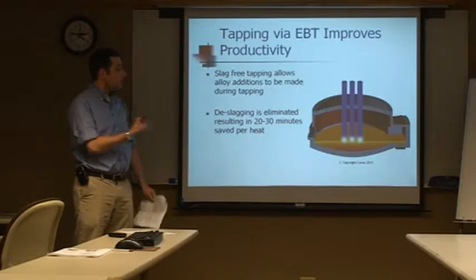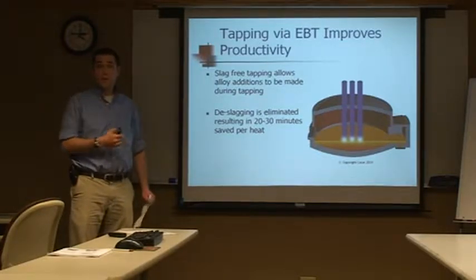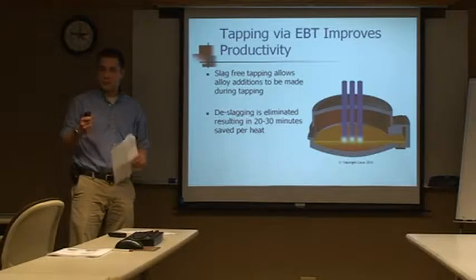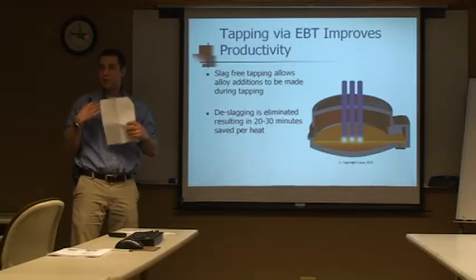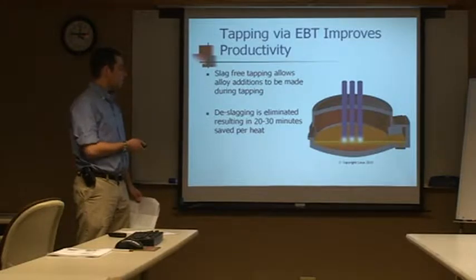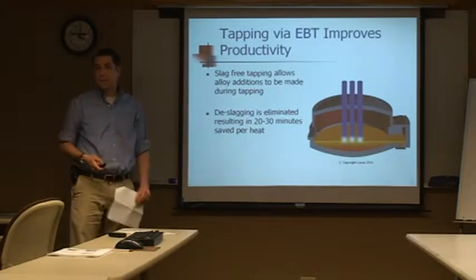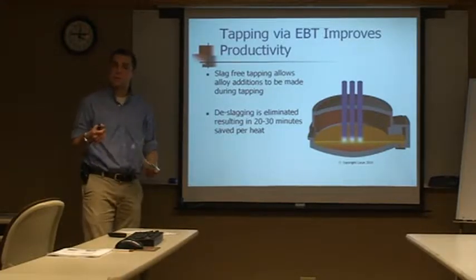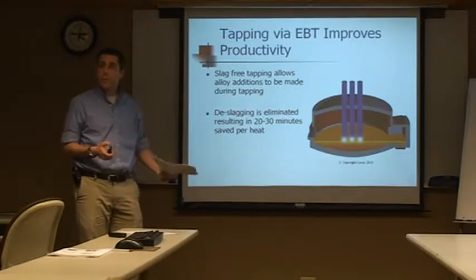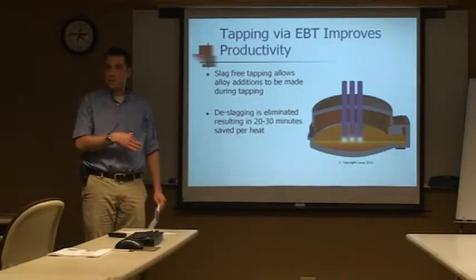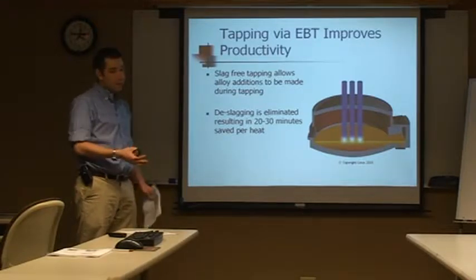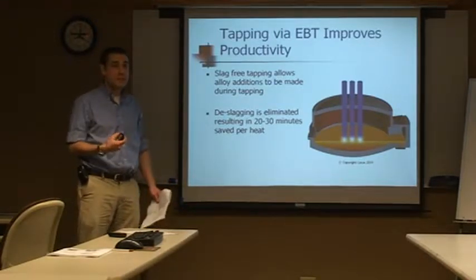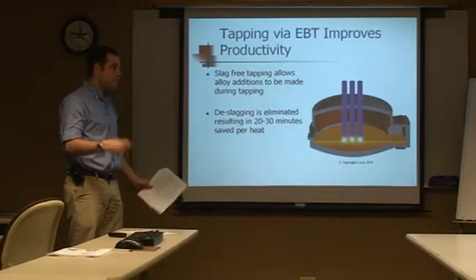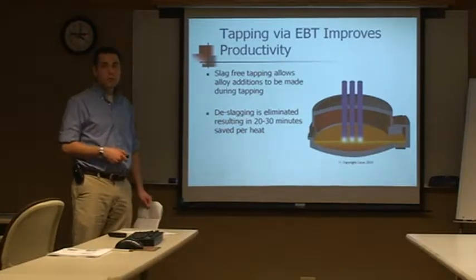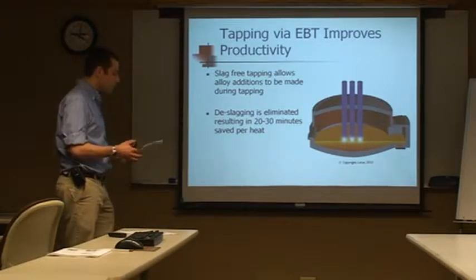So if we didn't have the bottom tap, we'd have to do a deslagging operation, which is where you take a rake and you rake off the slag and put a new one on top. This eliminates that operation and saves us about 20 to 30 minutes per heat. We do still have the capabilities to deslag heats, because we have to do it every once in a while if we need to drain the furnace completely for any reason. That, of course, includes the arc furnace slag, so we'll have to deslag that heat. But I'd say over 90% of the heats that go through, we get to skip that deslagging operation.